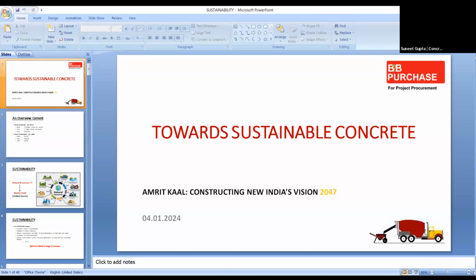But in the past, the initiatives that have been taken by the cement industry in the country are that, yes, the carbon dioxide emission has been reduced by 36% from 1996 levels. Earlier, it was 950 plus kg per ton of cement production. Now it has come to 665 kg. And the share of cement with reduced clinker content has increased to 75%. With the same strength levels, with the same properties the customer desires, the clinker has been reduced, and the share of such cement has gone up to 75%.